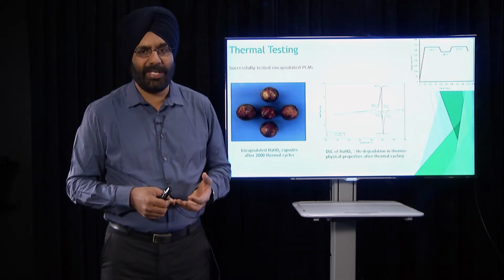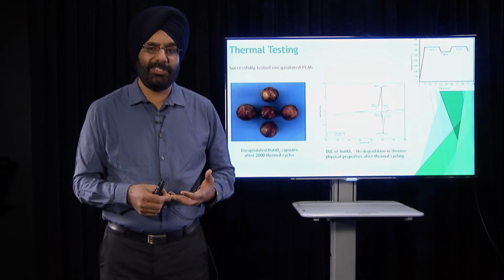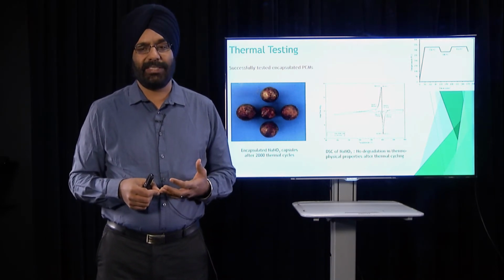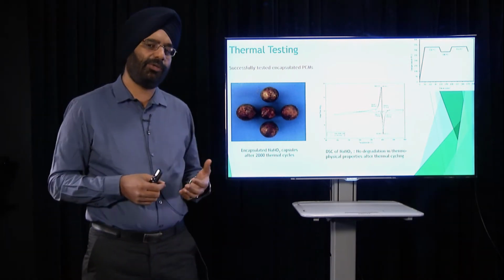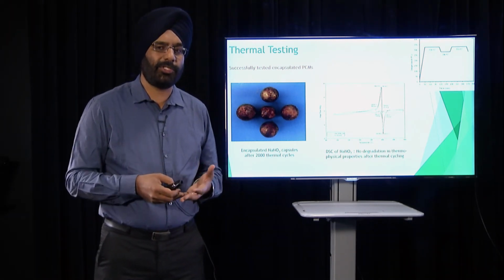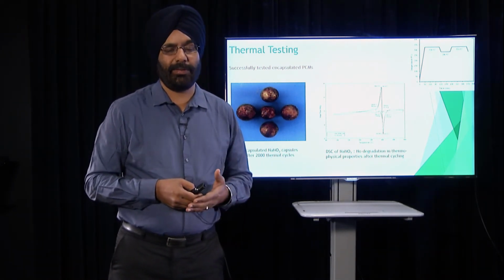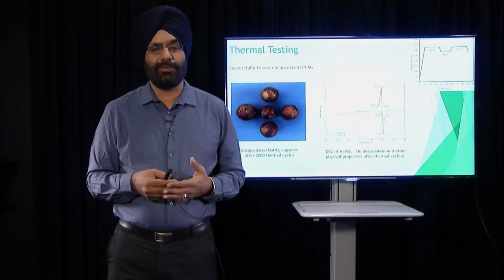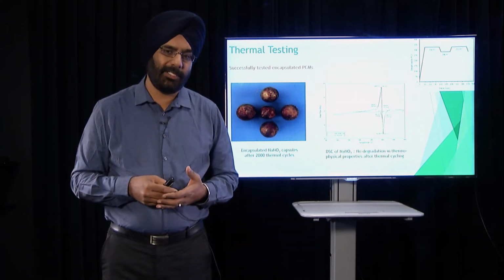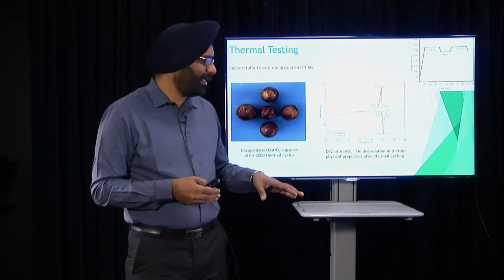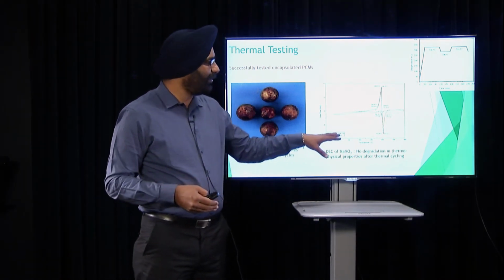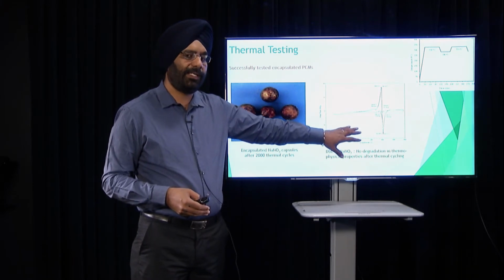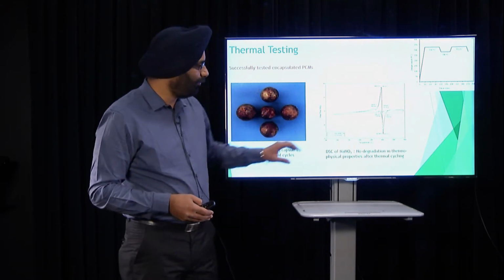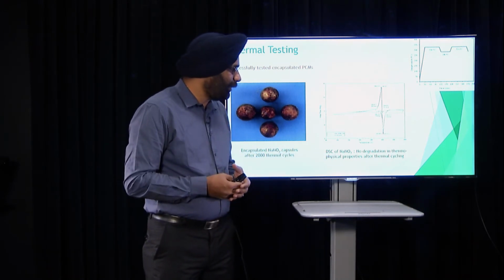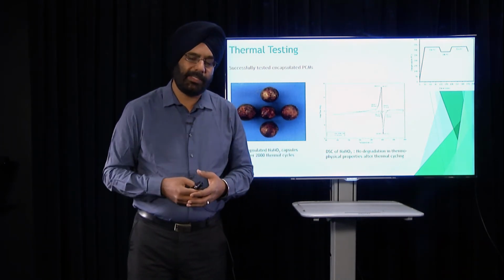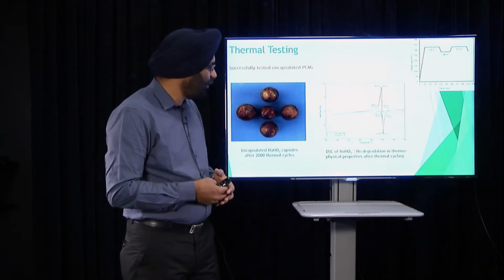Its melting point will change. Its energy density will change. Its latent heat, the delta H, will change. So we wanted to know what happened to the salt inside the capsule after so many cycles. After passing around 2,000 cycles, we cut open the capsules, took out the salt, and tested it for its melting point and also the delta H, the latent heat of fusion. The instrument used was the DSC, the differential scanning calorimeter.